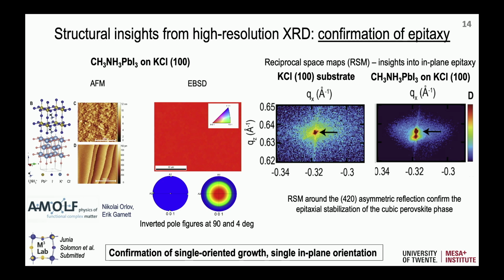And one of the nice things is here in AMOLF, we collaborated with Nikolai Orlov and Erik Garnett, and we said, can we do EBSD on this sample to see if it's really single-oriented? And if you are used to seeing EBSD, you will be surprised about this. Or at least we were very surprised. We were like, okay, this is fake, right? You can make a red square, that's it.